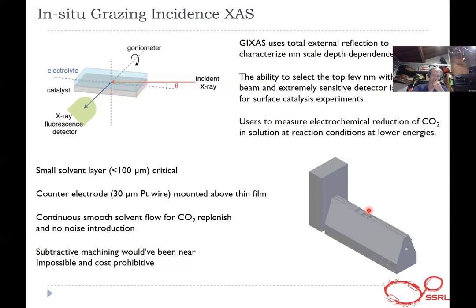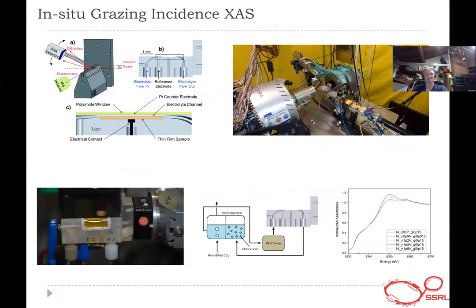You can see we have a platinum wire counter electrode that mounts above it, and it's a 30 micron platinum wire. And we have to have a continuous smooth flow of CO2 saturated solvent, and it needs to be smooth so we get no noise introduction. The solution we came up with, because subtractive machining, what your standard machining would have been, was near impossible or extremely expensive, was these 3D printed cells. You can see we have flow in, flow out, a small form factor reference electrode, the two platinum wires over the top, a small electrolyte flow, and that's all covered in Kapton.